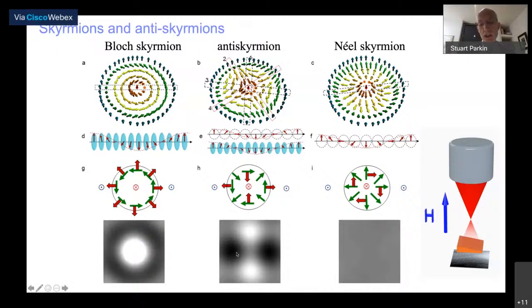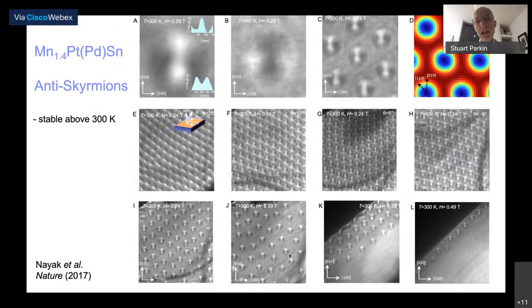And in the middle, you can see the anti-skyrmion. Because of this complex domain wall structure, it forms this cloverleaf pattern where you see increased intensity, these two white regions vertically, and horizontally these black regions of decreased electron intensity. So it has a very characteristic pattern. And this pattern is what we saw in a Heusler compound for the first time, an anti-skyrmion.